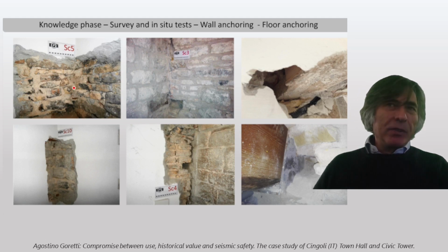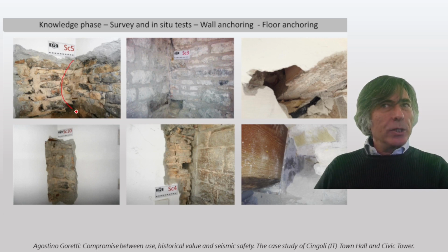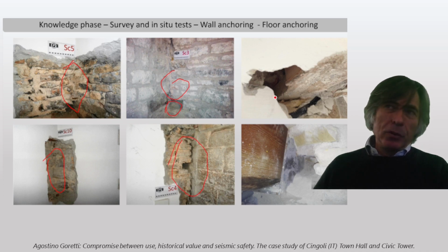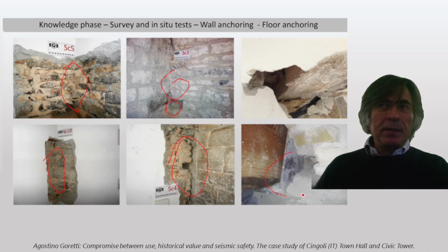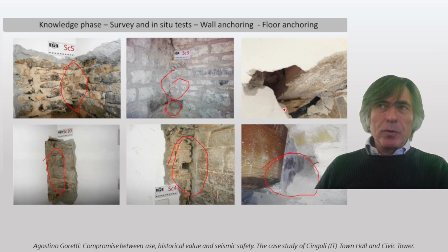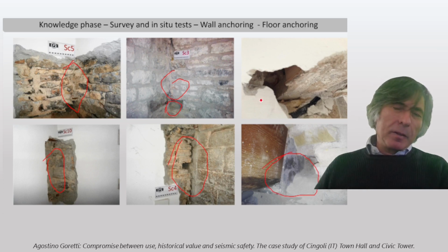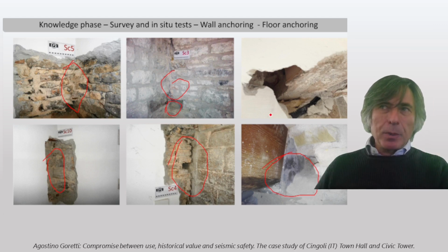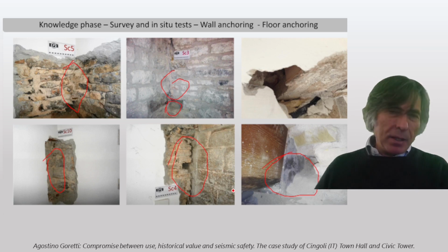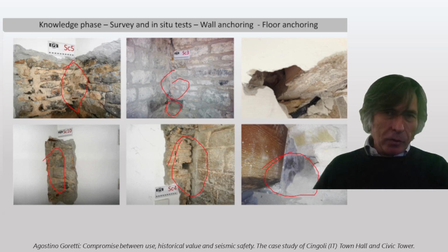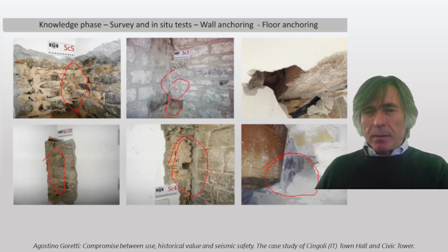Anchoring of the vertical walls at the corners: there are several situations. In this case it's well anchored, in this case also it's well anchored, in this case it's anchored on one part and not on another, and in another case it's totally not anchored. While for the floors and for the roofs, due to the presence of steel plates in the roofs, and because the joists are prolonged into the walls, and there are very often tie beams or ring beams, not reported in this picture, or beams resting on the masonry walls, the floors can be really considered well anchored to the walls.